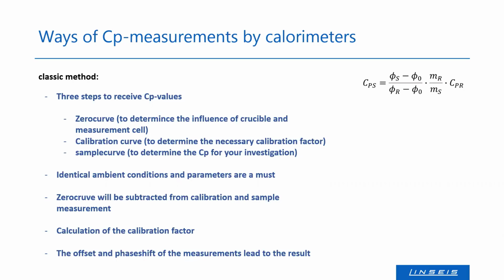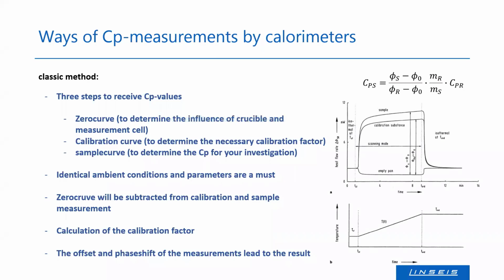What's important for these 3 measurements is that we need identical ambient conditions and parameters. So we need the same heating rate, in the best case the same temperature range, and also the same atmosphere, and so on, the same crucible. This is pretty important here. The zero curve will be subtracted from the calibration and the sample measurement, and then we can calculate the calibration factor. So what are we looking at here? We've got these 2 measurements with the correction measurement, and we look at the offset and the phase shift of our measurements. And this is how we receive our CP. Here you can see on the right now the temperature profile at the bottom.